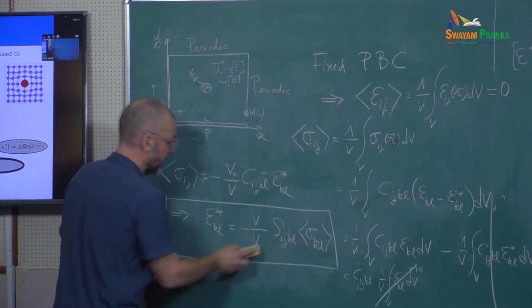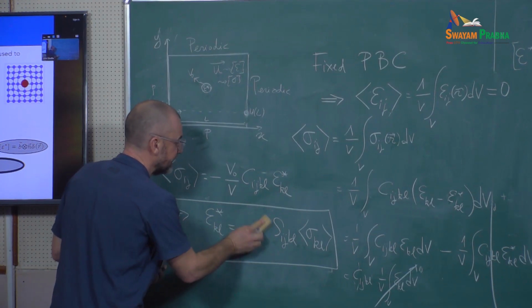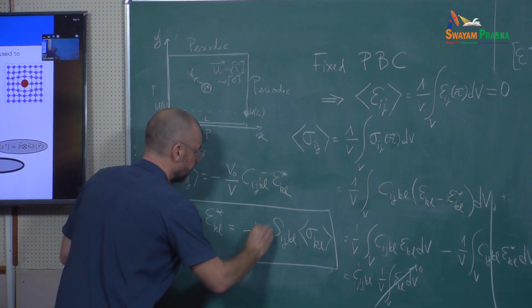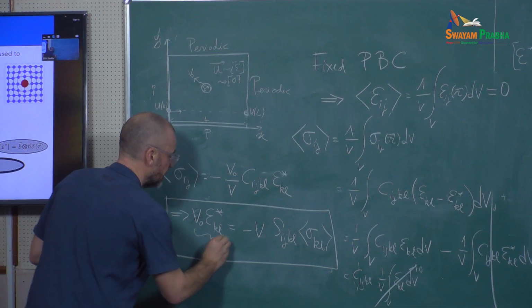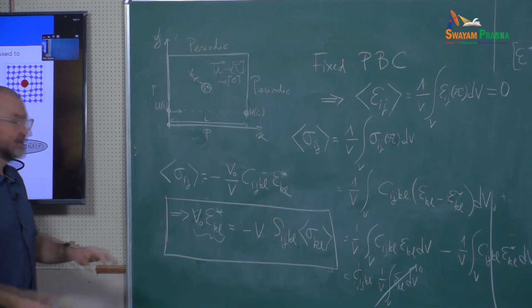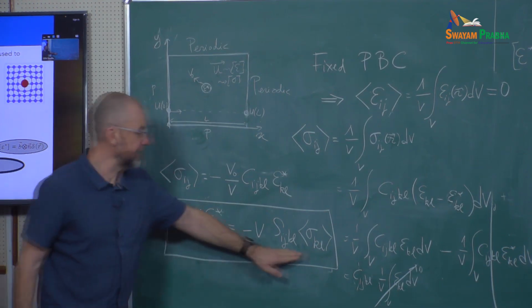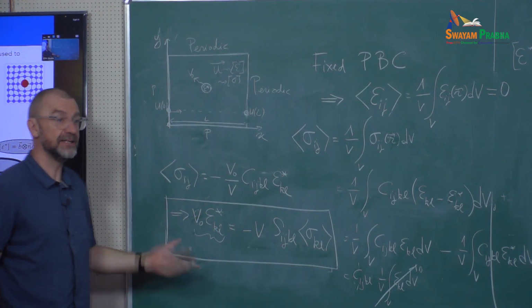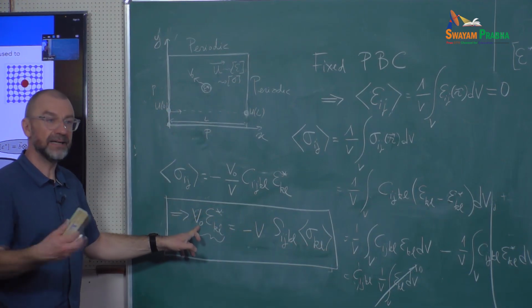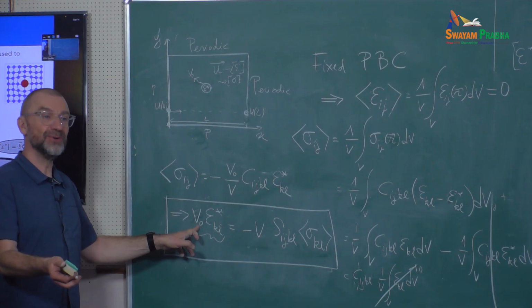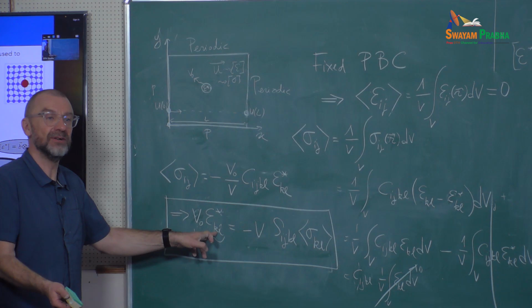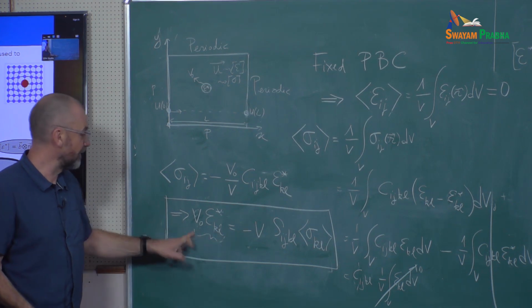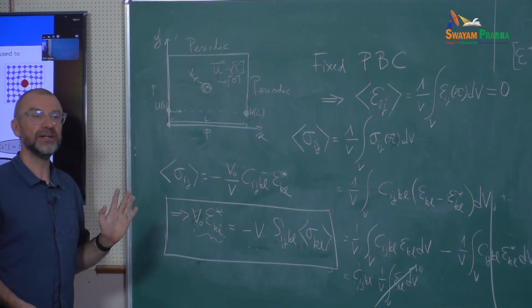So actually what is really given by the simulation, this term here, is a constant. It's something which is given by the elasticity. V0, I can choose its value. If I change the value of V0, I will change the value of epsilon star, but such that the product of the two will remain constant.